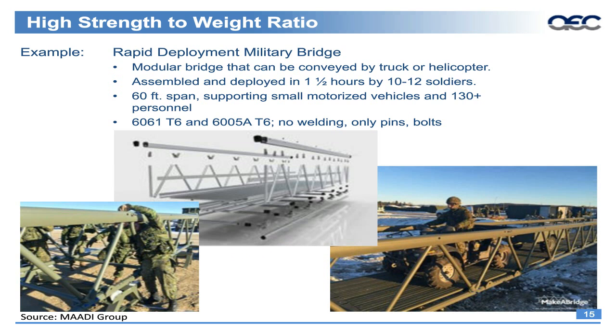Here's an example in basically a bridge application. So here in building and construction, weight not only is important because you need to be able to transport this, but also because you are assembling this in the field. So with this particular application, you're looking at transporting this into remote locations by a truck or a helicopter, which is very important to have a lightweight structure. But then you're also looking at quick assembly, assembling a bridge in only an hour and a half with a relatively few number of workers, in this case 10 to 12. But yet it can span up to 60 feet.